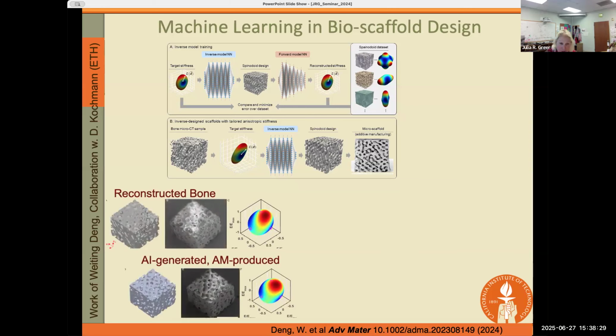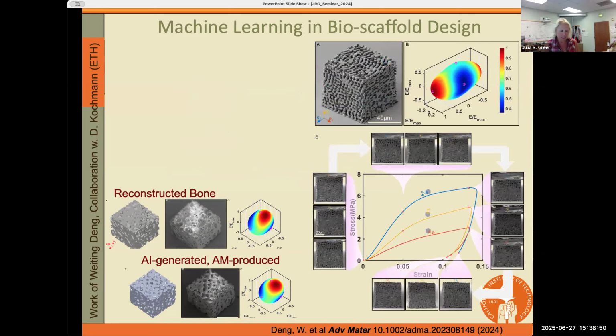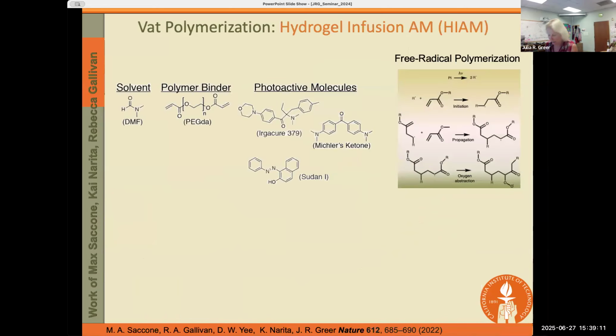This is our collaboration with Professor Dennis Kochmann, who basically developed the model. And then what my student did is she reconstructed trabecular bone. What you see here on the left is an actual tomography of trabecular bone. And then she was able to print both the reconstructed bone and the AI-generated sample, and then she was able to measure their stiffnesses. So what you're seeing here is the real data that shows that they are, in fact, anisotropic. And that's not something that you could have easily predicted by simply looking at this structure. In fact, most people who would look at this structure would think that it were isotropic. So this was a really neat application of machine learning.